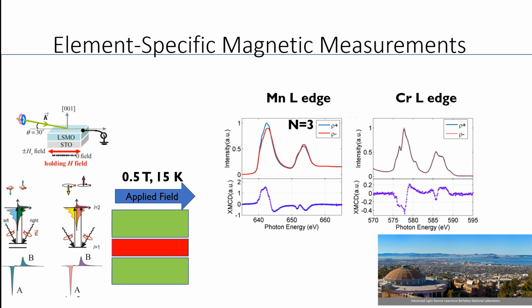This effectively measures how much of your sample, the spins, density of states have an up polarization and a down magnetic polarization. If your material has no net magnetic moment, then these two, the blue and the red curve, are going to be the same. If your material has a net moment, you can see that these two curves are not the same, and there's a difference that I'm plotting down here, which, if you integrate, gives you a positive value. So the positive value you get here tells you that the spins in the manganese sublattice are aligned in the same direction as your applied magnetic field.